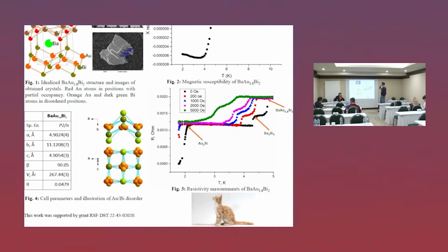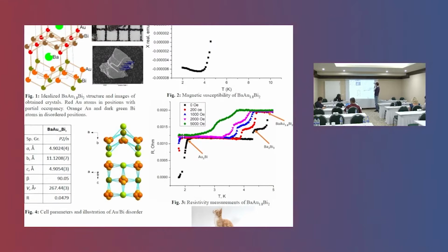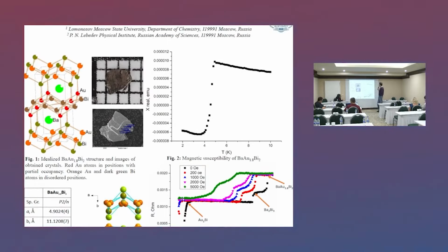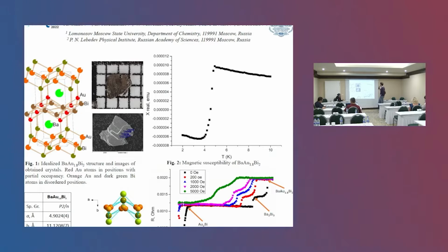We obtained our crystals with a pretty standard self-flux technique, which can be found everywhere. We just used a simple alumina crucible, which was sealed in a niobium tube, and later this tube was sealed in a quartz ampoule to prevent oxidation in a muffle furnace. We were also able to measure magnetic susceptibility, which can be found on this plot. We found a superconducting phase change at about 5 degrees Kelvin.